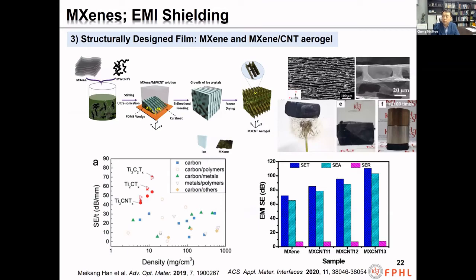Yuri and my groups also reported the EMI shielding properties of well-aligned and highly porous MXene and MXene CNT hybrid aerogels. This aerogel was fabricated by bidirectional freezing method. That aerogel revealed a well-aligned lamella-like porous structure supported by columns. The prepared aerogel was light enough to stand on a flower without collapse, and it also had very strong mechanical property and good shielding performance, even at very low density, 0.06 gram per cubic centimeter. Such shielding performance is attributed to the improved absorption property that is caused by improved internal scattering at the internal multiple interface.